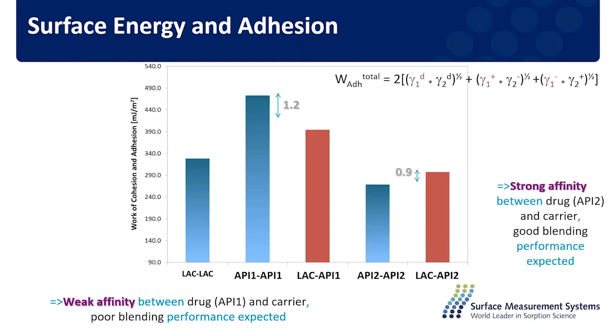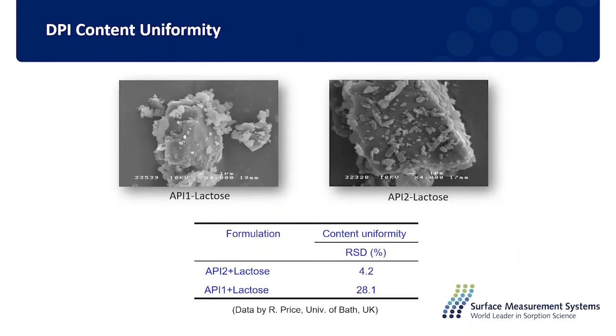But in the case of API2, you can see the ratio is less than 1, and the adhesive energy with the lactose is high. So in this case, we expect strong affinity between the drug and the carrier, and also good blending performance, because there's very small affinity between drug particles, smaller than between the drug and the carrier. Since API2 should have better blending performance with the lactose, the content uniformity results supported this. As you see in the table, API2 has much better blending performance. Its content uniformity also has a much lower RSD value, which shows that the blend is more uniform compared with API1.